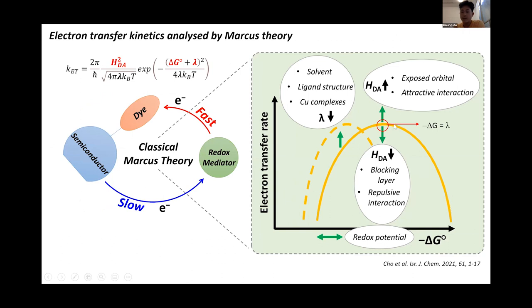this Marcus parabola. The Marcus parabola is often obtained by fitting the measured decay rate as a function of delta G using the Marcus theory of electron transfer equation, because it tells us the reorganization energy, which equals the delta G at the top of the curve, and how high the electronic coupling is, based on the location of the top of the Marcus curve. So again, the important thing is to determine the top of the Marcus curve, which has the fastest charge transfer kinetics.